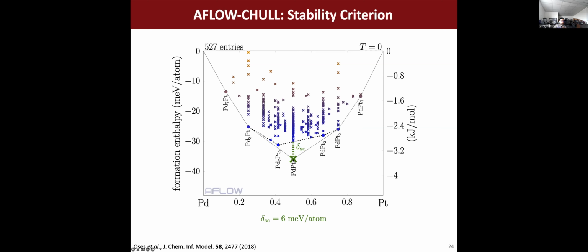So what we do is we do sort of a perturbation here. We take this system, let's say we're doing an analysis of this system, we remove it from the convex hull, recalculate what the new convex hull looks like without this system, and then calculate that distance from the true convex hull. So this is called the stability criterion.